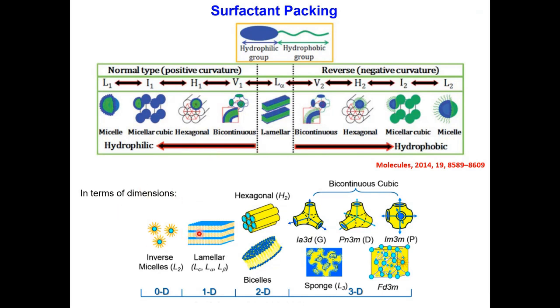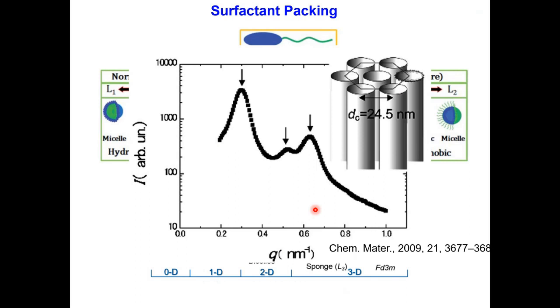In terms of dimensions, micelles are 0D systems, lamellar phases, where the surfactant forms layers like membranes, are 1D systems. You can have hexagonal phases, bicontinuous cubic phases, and so on. This is one example of a scattering pattern from a hexagonal system of a surfactant. I would like to tell you what I mean by hexagonal mesophases. If you have a soap bar in your home, and you remove that soap, it has a little bit of water underneath, and you will see a slime underneath. If you take that slime and watch it under the microscope, you will see beautiful textures. These textures come due to surfactant packing. They might be lamellar, or hexagonal, or some other type of structure, but they can be characterized very well using small angle X-ray scattering.